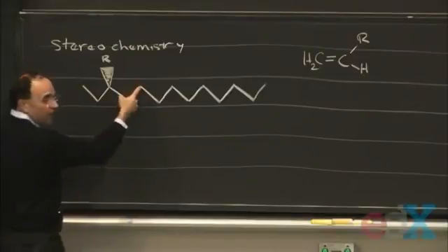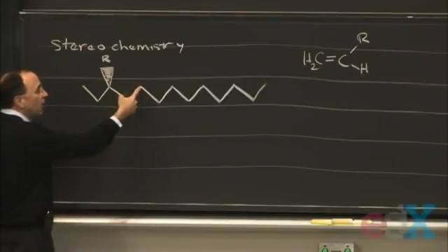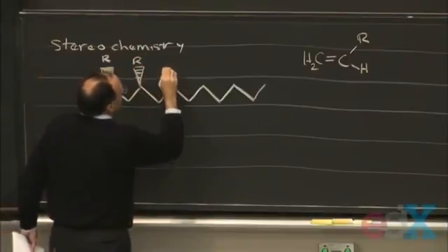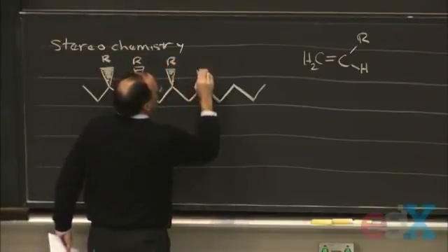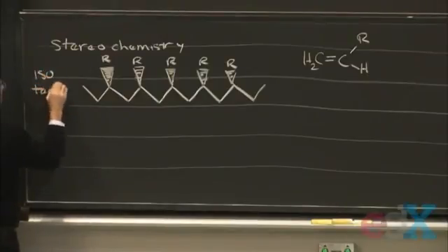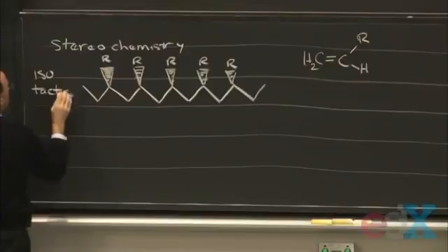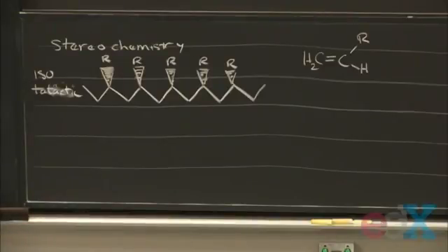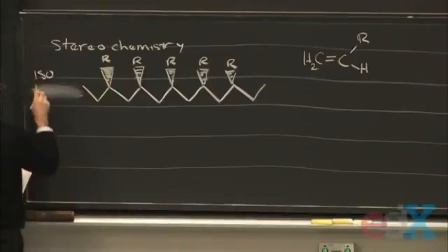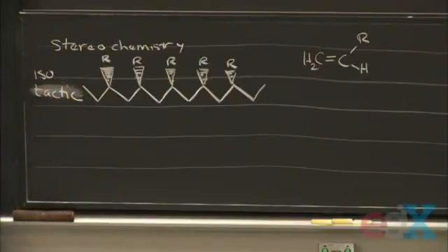So every other carbon, I go here, now I have a choice where I can put it, right? This is the stereochemistry part. I can either put it behind or in front. If I put every other one in front, we call this isotactic. Isotactic. Let me get it correct. Now you can read it. Isotactic, because each mer shares the same stereochemistry.